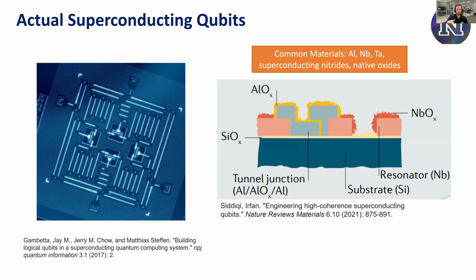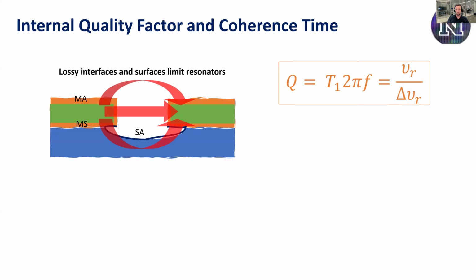Setting aside deposition-related sources, you can see there's going to be a native oxide on that aluminum. There's going to be interfaces all over the place. Electromagnetic fields are participating in everything. So let's think about, well, which sources of losses do we care about? All right, I'm going to separate this out to three interfaces: metal-air interface, metal-substrate interface, and the substrate-air interface. Electromagnetic fields are participating in all of this. Now, you don't get a ton of loss in the superconductor, as we shall see, but those electromagnetic fields are participating in all of these different interfaces.